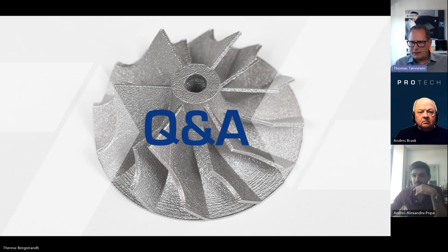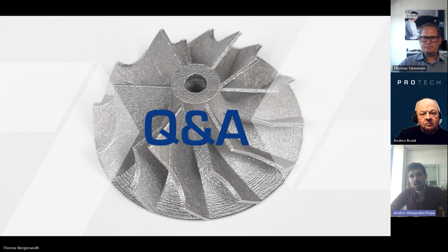Okay, this is from Jose, and he says, what are some key design considerations or best practices for creating parts specifically for 3D metal printing, referring to the battery holder, for example? Again, it depends on what you want to get out, but since I can use 3D printing to enter a virtually limitless design space, can I use the least amount of material I need? Can I optimize the shape for design for additive manufacturing? So you think about whether you should decrease the wall thickness to, let's say, 1 millimeter, so that you can save this material. But then the next question is, if you build something very thin and tall, the thermal gradient up here might mean that it's probably going to delaminate in that area.